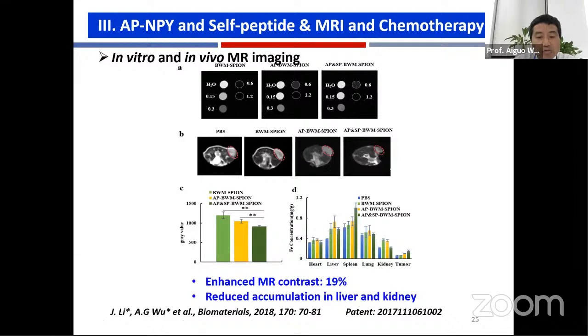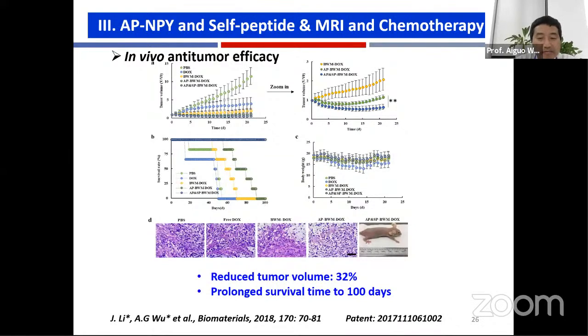And also, according to the MRI contrast, we found it can enhance the MRI signal, and also reduce the accumulation in the liver and kidney. So usually nanoparticles accumulate there, but after conjugation with the AP-NPY, the accumulation is reduced. And also we found very good chemotherapeutic function. For example, it reduced the tumor volume by about 32%. And also the nanoparticles let the mice have a prolonged survival time of 100 days. And for the control group, all mice are dead.